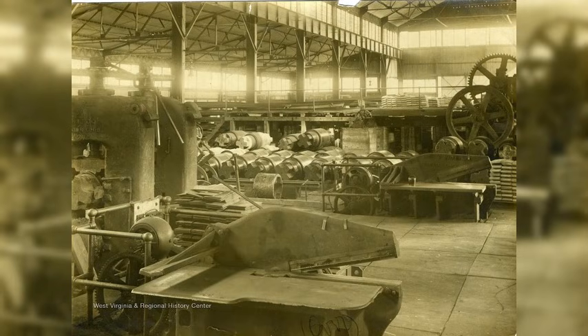The government was willing to fund capital investment, and food manufacturers were desperate for any solution that would keep products on shelves. The first modern electrolytic tin plating line in the United States was already under construction when the war began at the U.S. Steel plant in Fairless Hills, Pennsylvania. Construction accelerated dramatically in 1942. Other steel mills began planning similar lines. The elegant process: clean steel strip passed continuously through electrolytic baths containing dissolved tin salts. Electric current caused tin ions to migrate from solution and deposit onto the steel surface. By controlling current and line speed, operators could precisely control coating thickness, far more accurately than hot dipping ever allowed.